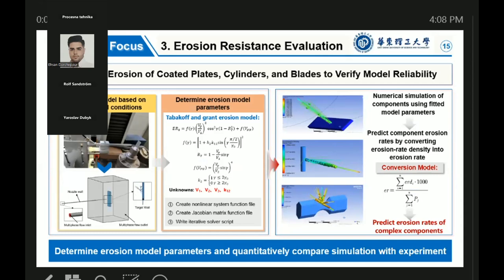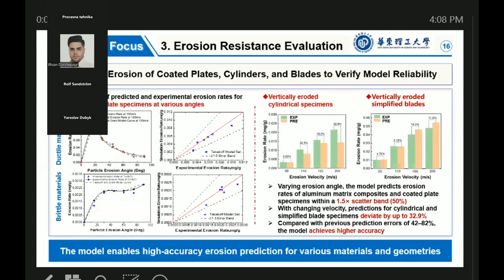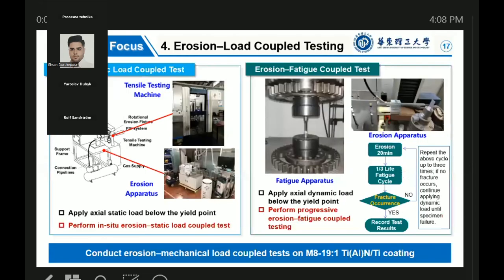The predictions agreed well with the experimental data. For plate erosion, error fell within a 1.5 scatter band. For cylindrical and simplified blades, the maximum error was 32.9%, which is significantly lower than reported in previous studies. This confirms the model's accuracy across materials and geometries.